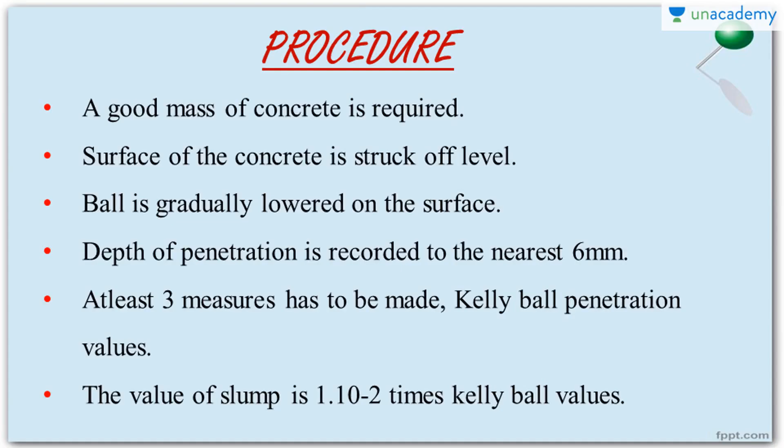The procedure is very simple. First and foremost, a good mass of concrete is required as the test sample. One advantage of the Kelly Ball test is that it can be done on site — if the concrete is placed in a hopper or a small container used to transport it, the Kelly Ball test can be performed there. But you need the concrete in a minimum depth of 20 centimeters. The surface of the concrete is struck off well to create a level surface, and no further working is done on it.